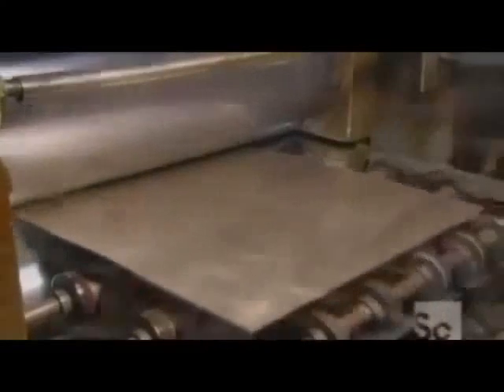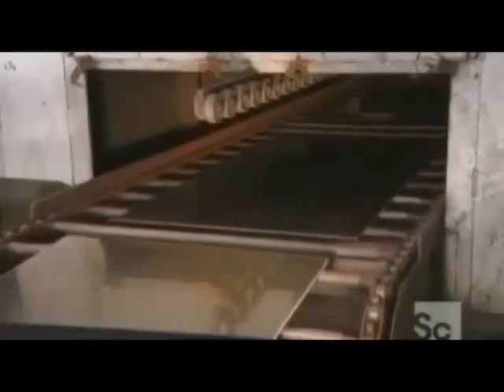From the oven, the metals enter the first mill, which uses electric current to heat and bond the three layers into one. Now it's into a second rolling mill. This one strengthens the bond. That steam you see is the water-soluble lubricant evaporating against the hot metal. Now the bonded metal travels to a second oven for reheating. This further strengthens the bond. From there, it's into a 110-ton press. It forces down a die to cut out the starting shape of the piece of cookware they're making.